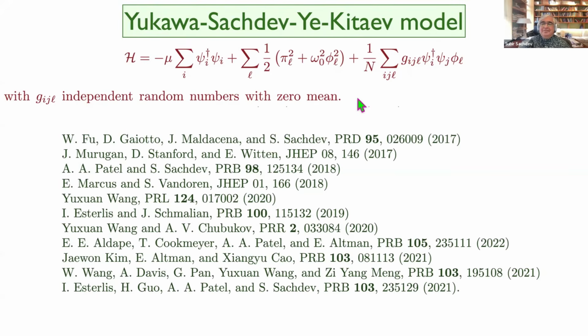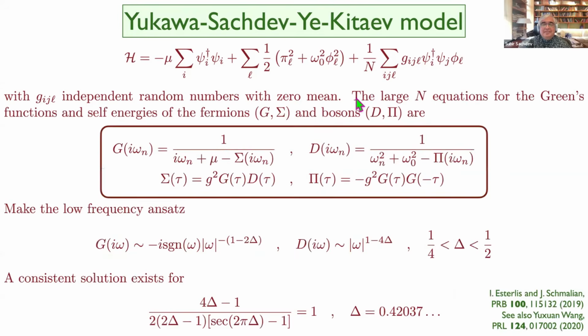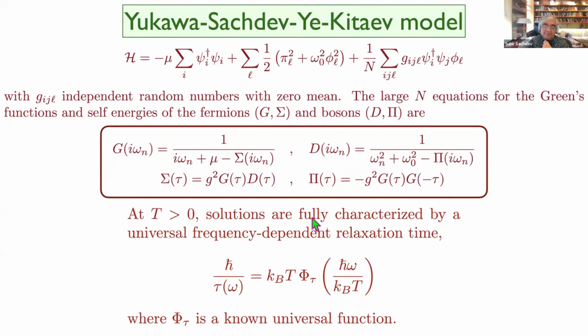All right, so this model turns out to be solvable in the large N limit, and really a lot is known about it today, partly due to all the dualities to black holes, which I won't talk about here. But at N equals infinity, everything reduces to solving these type of equations, which are essentially the Eliashberg equations for electrons and phonons, but with no momentum space. And in this zero-dimensional form, these give you, in fact, critical solutions for all values of the coupling g. And in particular, you get this very important feature, which people now call Planckian relaxation: the characteristic relaxation time, or thermalization time, so the system will thermalize on its own, and the time it takes to thermalize is just h-bar over kT. In fact, it's the shortest possible time. And it's independent of the coupling g, which is quite remarkable.